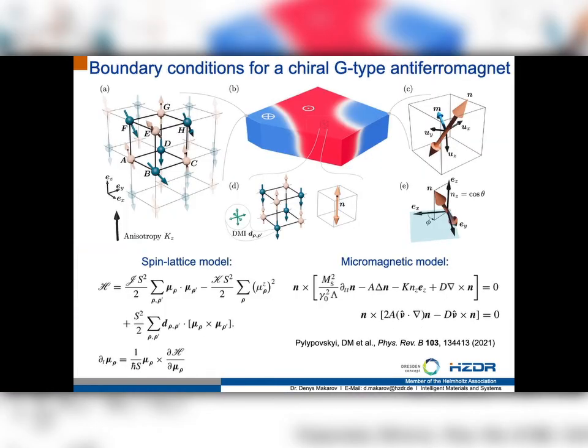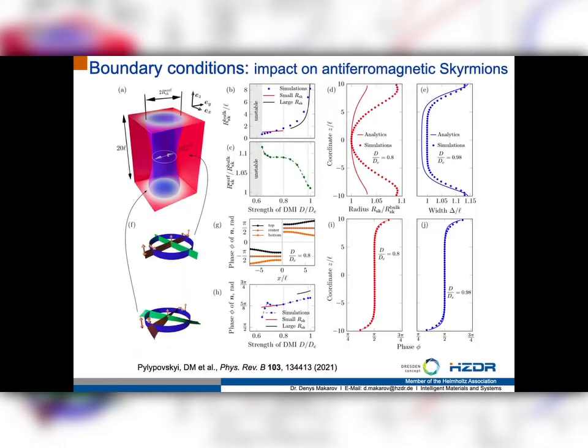You can analyze what would be the effects of boundaries on a G-type chiral antiferromagnet. Again, you can formulate a transition from spin lattice to micromagnetic models. You can derive properly the boundary conditions here. And you can see that as soon as a domain wall comes to the boundary, it gets deformed. It gets, for example, such a twist. It gets broadening, for example. And this is happening at relatively large distances. So in principle, if you want to have bulk-like properties of domain walls, you will need to have your system at least 5 to 10 exchange lengths wide. Otherwise, the modification of the texture due to the boundary effects will be so substantial that you will not have bulk-like properties. The same is valid for Skyrmions.